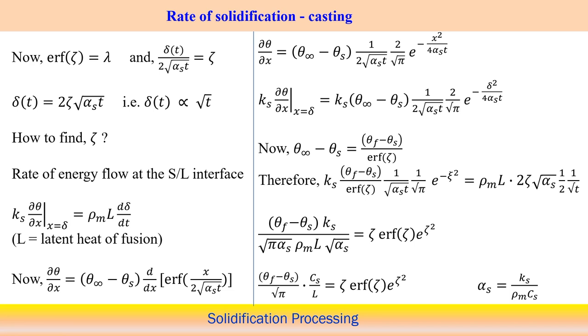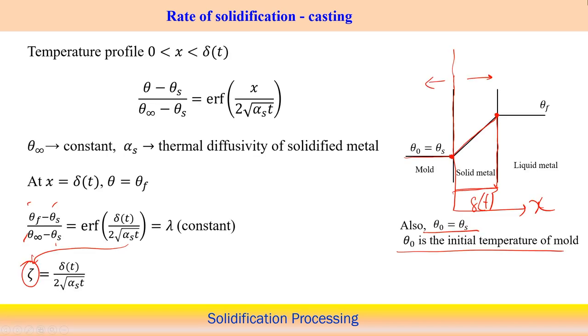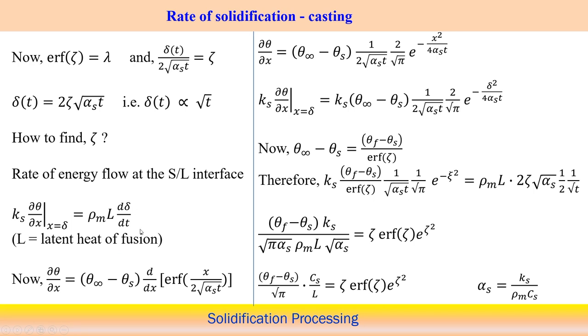Now we are getting from the equation that, if it is zeta, this is the error function of zeta equal to lambda here also, with theta minus theta infinity. So when the error function argument is zeta equal to lambda, because lambda is a constant here, it means that delta t by 2 root alpha s t is zeta. So from here we can calculate delta t equals 2 zeta root of alpha s t, that we are getting from here also. It means that delta t is proportional to the square root of t, assuming the other terms are constant. Zeta and alpha are constants in this case.